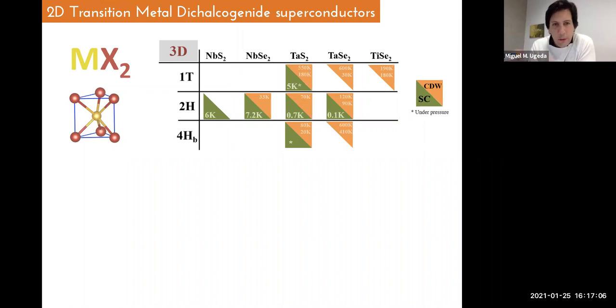For those of you who are not familiar with this family of materials, these superconductors basically follow this stoichiometry with one transition metal element here at the center, surrounded and sandwiched by two planes of chalcogen atoms. Here I list the elements that form TMD materials that are superconducting in three dimensions, in bulk. In general, even in bulk, the superconductivity coexists with charge density wave phases. For example, the most prominent case is niobium diselenide, which has a critical temperature of 7.2 Kelvin and a charge density wave transition of 33 Kelvin.